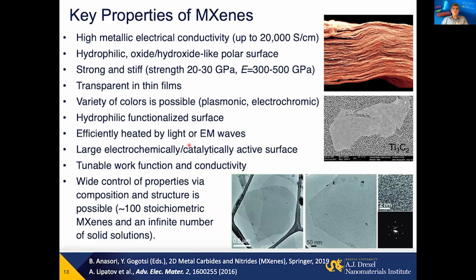So what are those key properties which make MXenes useful, which make MXene a really new addition to the family of 2D materials? First, as I mentioned, high metallic electrical conductivity. For example, in multi-layer films like this, with a lot of junctions, a lot of flakes, we currently get about 20,000 Siemens per centimeter, at least an order of magnitude higher conductivity compared to, for example, reduced graphene oxide.